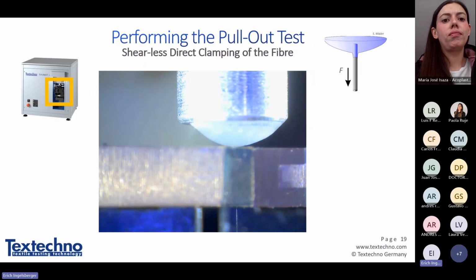Now it is touching with the perfect alignment. In the last step here, we reduce the free length of the fiber to reduce or eliminate as much as possible the elongation properties of the fiber. Then we close the clamp and start pulling the fiber out of the matrix.